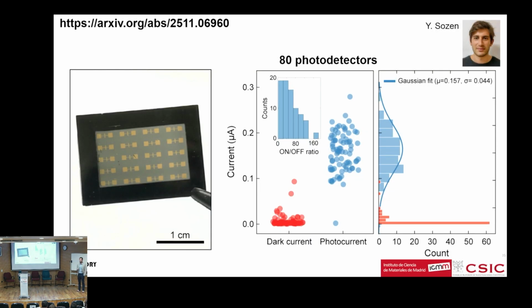And one of the nice things about this production method is that it allows you to fabricate devices in batch. Okay, so with a very simple technique, for example shadow mask evaporation, you can fabricate batches of 80 devices, like this case here. There are 80 photodetectors fabricated on silicon oxide. You can fabricate many of them, and then you are limited by how fast you can characterize the devices, actually. So now the limiting factor is not how fast we can produce the devices or what success rate or yield we have in the fabrication, but how fast we can characterize the devices.